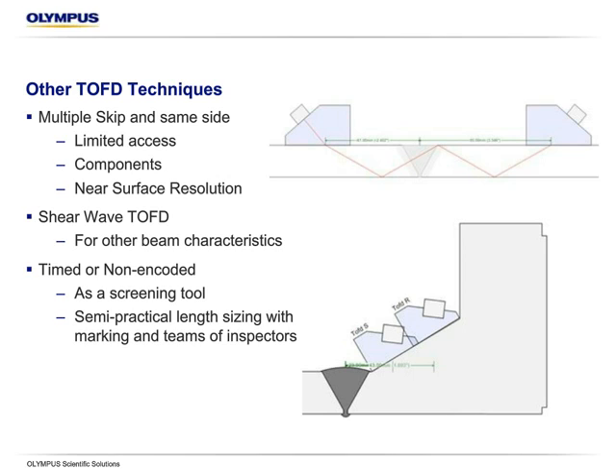There are instances where we actually use the shear wave component as our main component, so we have to have specialized wedges. We do this for certain sizing characteristics and also in a lot of the multi-skip because shear waves give us a better dependent skip off parallel surfaces. And in some cases we'll do timed with no encoder, but this is pretty uncommon. Sometimes with two-man teams it's possible if a guy actually had some markings, he could do some really quick screening and get some semi-practical length sizing, but it's not going to be as accurate as using an encoder with a scanner.